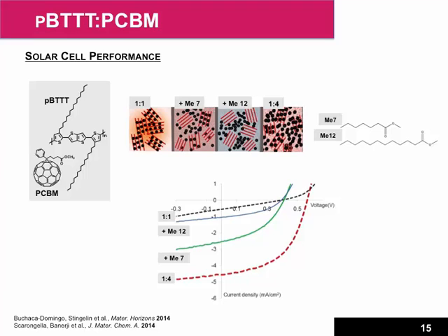Then you can add more fullerene, and since all the places inside the polymer are already filled up, the excess fullerene will form clusters around it. So here you get two phases. You get one phase which are the intermixed bicrystals, and one phase where you have extra fullerenes clustering around it. And this gives the best solar cell efficiency. So the fact that you have those pure fullerene domains seems to help the efficiency.